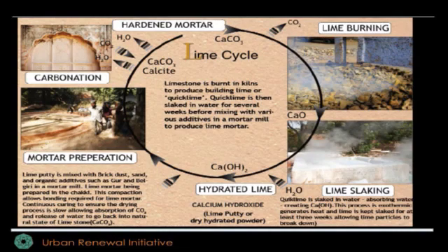Those microns are then taken, and I don't know whether that image is clear, and I'll show you a better one in a minute, in an aate ki chakki, we've all seen a grinding stone. Lime is put, and it's mixed with sand. 1 lime, 3 sand, and mixed so that each and every particle, micron of lime is covered equally with sand. And then it is used on a building. So you use it as plaster, as mortar. What happens? The carbon dioxide is absorbed and the water is given out, and it goes back into its natural state of CaCO3.